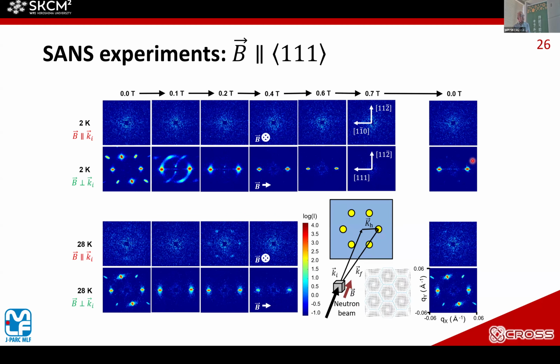And the second experimental condition is the magnetic field applied parallel to the neutron beam. It corresponds to the upper panel of each temperature. And for this condition, we can observe the skyrmion lattice. So in the A phase, 28 Kelvin is the A phase, we have observed the skyrmion lattice. It's very low intensity, but we have 6 black spots here. On the other hand, at 2 Kelvin, even in the B phase region, we don't have any black spots. So from this measurement, we can conclude that the B phase is different from the A phase. And also, we can point to the possibility of the shielded conical phase, like kappa 2.